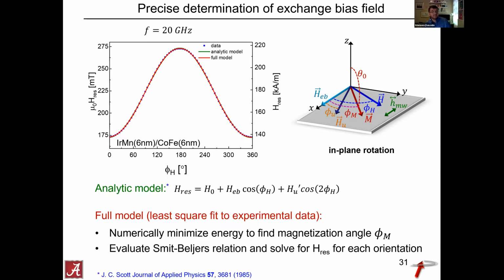experimental data. What we did here is we applied two models to the data. One is the analytical model that you'll find a lot in the literature, because you can write down an analytic expression that makes it easy to fit. The other one is a little more complicated. You take the Smit-Beljers relation, minimize the energy, find the angle of the magnetization, and solve for the resonance field for each orientation. Then you do that in a kind of fitting procedure to extract the parameters. So you can see why people might prefer the analytical model. And looking at the data as presented here, you might say, well, why bother, right? Why would you use something more complicated when you can get away with an analytical model, as it seems?